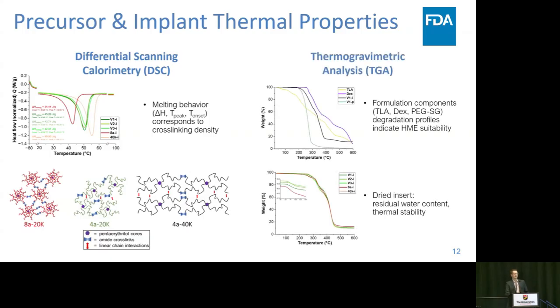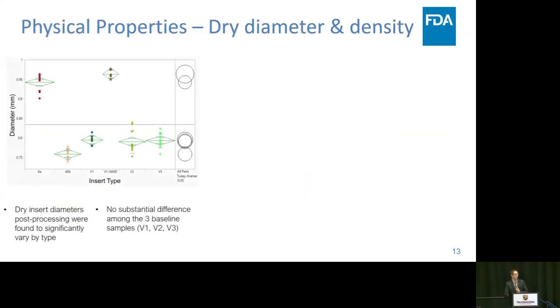Using TGA, you can look at the suitability for doing something like hot melt extrusion to process these, and look at the degradation profiles under higher temperature. And you can notice here that the TLA is the most sensitive to that. And this can be used to measure the residual water content and thermal stability of the dried implant product. We wanted to look at the physical properties as well, the dry diameter and the density.